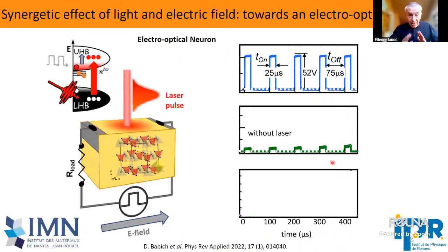All right. So before leaving this application-oriented part, let me show you a last example. Remember, I told you that the mechanism behind the electric Mott transition is most likely something close to an electronic avalanche effect that leads to a multiplication of the number of carriers. But if you think for 1 minute, if the key mechanism that leads to this insulator to metal transition is the multiplication of carriers, you might suspect that light can do the same.